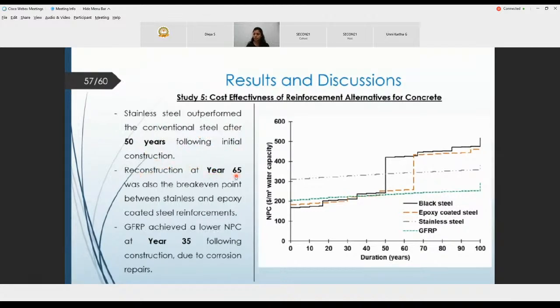Reconstruction at year 65 was also the break-even point between stainless and epoxy coated steel reinforcement, as seen here. GFRP achieved a lower NPC at year 35 following construction due to corrosion repairs.